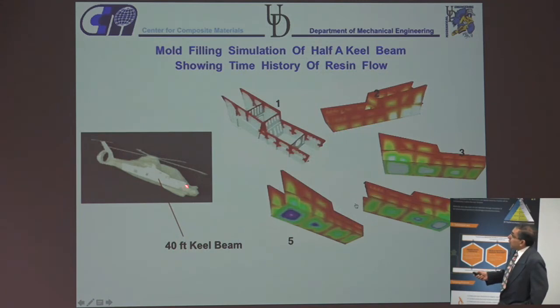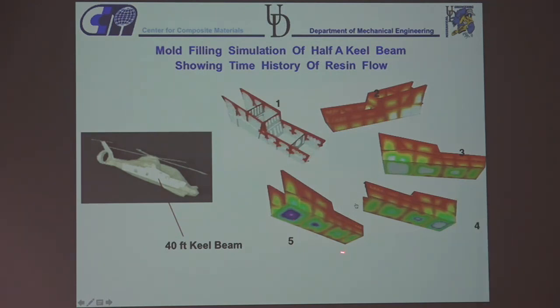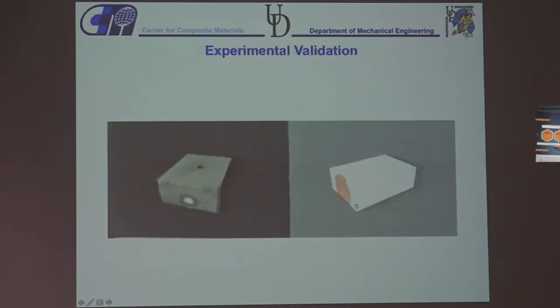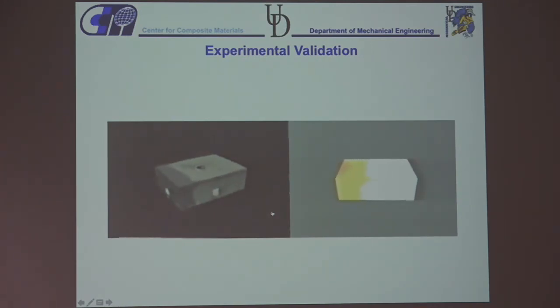I asked them to provide me the part much later on, 2 years later, and I just put some race tracking along the edges. I just said the resin flows 5 times faster in these gaps than in the bulk, and I was able to predict that the voids actually will occur in the bottom, because this is the region where the resin arrives last. So they were really very impressed that, even with not having much information, we were able to give them some answers. And this is another example which shows you how around the corners the race tracking happens.